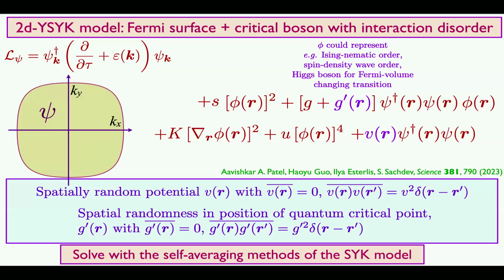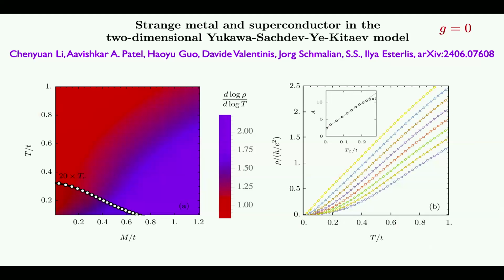You cannot just treat them as independent and add them up. You really have to take the whole thing self-consistently. In particular, there's another term here, which is the random Yukawa coupling that's really key. When you solve this theory with the same sort of methods that we use for the SYK model, this is what we call the 2D Yukawa-SYK model, you get exactly what's observed, at least qualitatively. This is the resistivity as a function of temperature for various doping. This is the resistivity exponent plot.